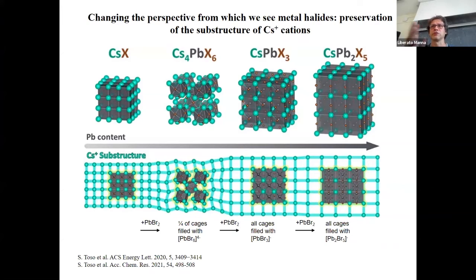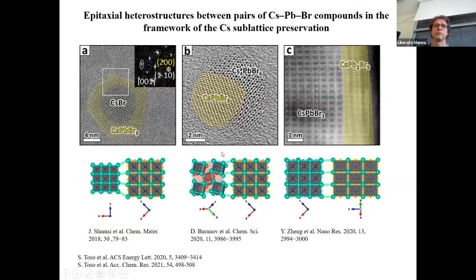And now, indeed, you can also see all the transformations we have been seeing so far, and also reported by other groups in the literature, as based on this preservation of the cesium cation sublattice. So, for example, the CsBr/CsPbBr3 core-shell structure I've shown you before can be seen on this slide. The CsPbBr3/Cs4PbBr6 also. And this type of heterostructure has not actually been reported on nanocrystals, but on bulk films. Also here, you can form an epitaxial interface, but only along certain crystallographic directions, because along other directions, the size of the cage is too large to accommodate any strain.